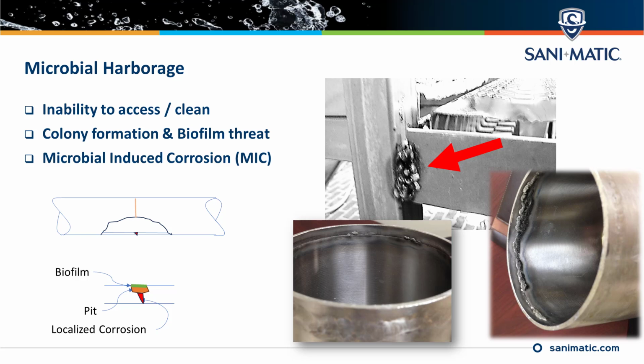What microbial induced corrosion is, you get a small spot that's non-cleanable, a pit, crack, a crevice, something like this. Microbes start to form in there. They actually will create a biofilm locally. They protect themselves from cleaning. And then it creates its own little environment where its excrement, for lack of a better term, is oftentimes highly acidic. It's going to continue to corrode and pit and create a localized corrosion, which then results in usually a blowout in the line. Sometimes, if you're lucky, you get a blowout in the line and you know it's there. Most of the time, you just end up with lots of localized corrosion that just continues to spread.